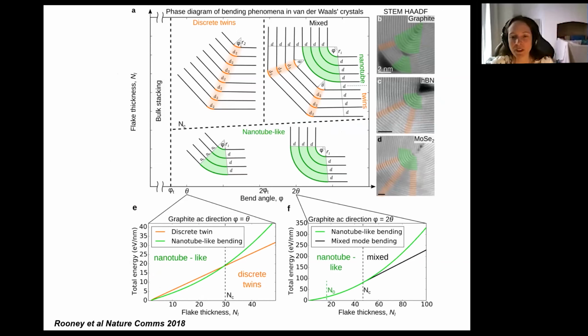and this, as I said, was done with the groups in Hong Kong Polytechnic University. So they've plotted out a phase diagram, and as you'd expect, when you have a thin flake, you get nanotube-like curvature. If you have a very small bend angle, you get strained bulk stacking. You get discrete twins for angles around the twin angle, and you get this mixed mode curvature when you get to larger angles.